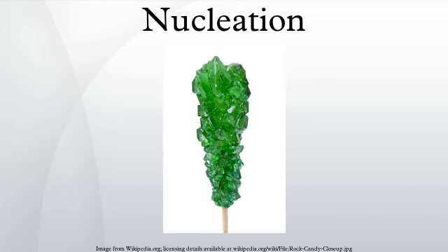To the right is shown an example set of nucleation data. It is for the nucleation at constant temperature and hence supersaturation of the crystal phase in small droplets of supercooled liquid tin. This is the work of Pound and La Mer. Nucleation occurs in different droplets at different times, hence the fraction is not a simple step function that drops sharply from 1 to 0 at one particular time. The red curve is a fit of a Gompertz function to the data. This is a simplified version of the model Pound and La Mer used to model their data.